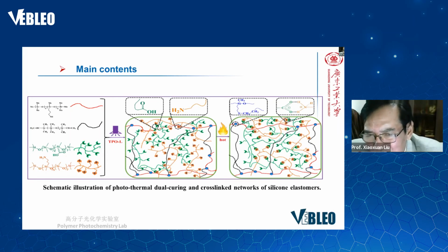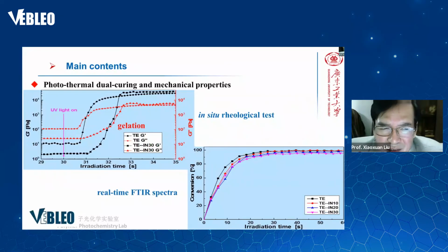And after that, we can apply heating. We can heat to different temperatures, and the silicone and some hydrogen bonds form the cross-linking networks. So this is the photo and thermal dual curing mechanism.